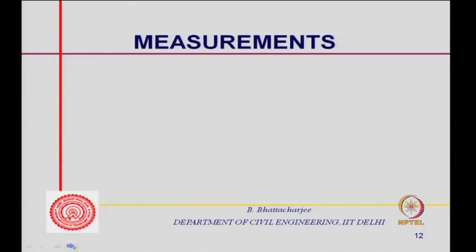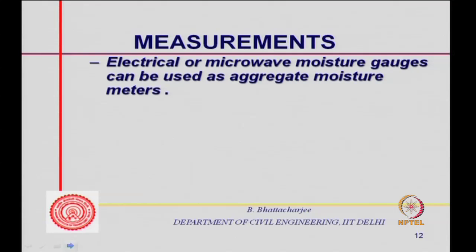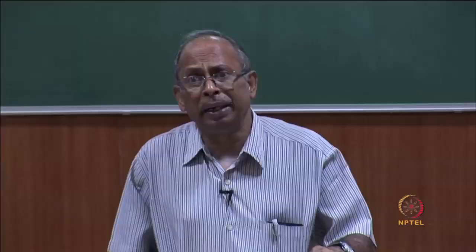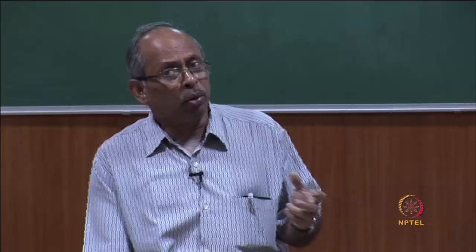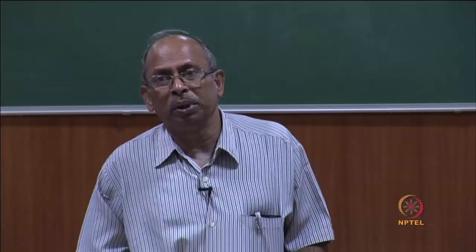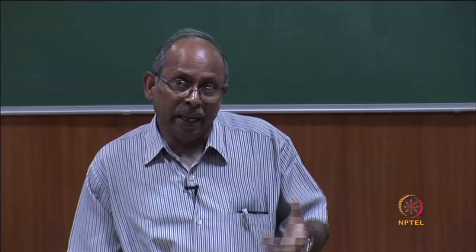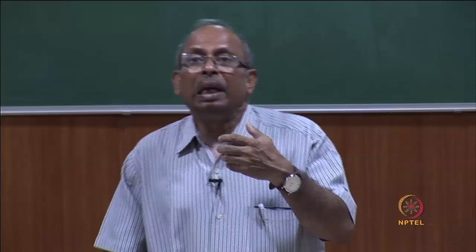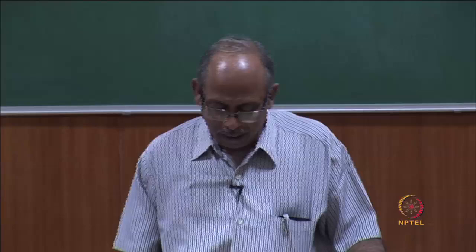Moisture gauges are usually of the electrical resistivity type, but microwave moisture gauges are available, which you just insert into the aggregate, and they will tell you the moisture content. It is desirable that the moisture content of the aggregates is measured all the time and corrections are applied in your mix proportion, because the added water will then be less, since some moisture is there in the aggregate, and the total aggregate quantity will be more. If you have SSD condition aggregate, the quantity you need has to be adjusted depending upon the moisture condition, and therefore moisture should be measured all the time.